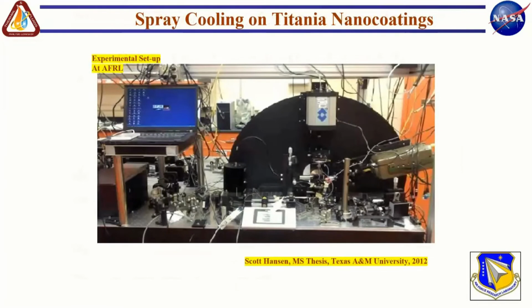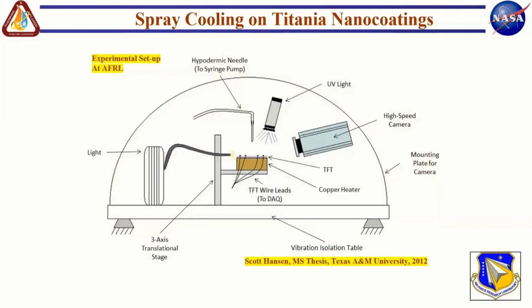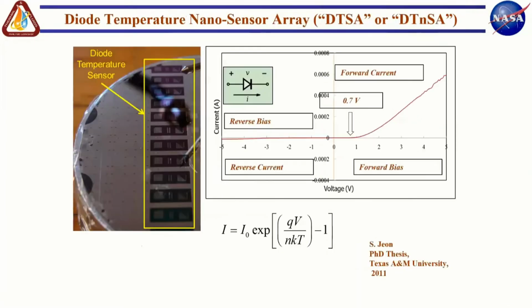One other work I wanted to showcase is Scott Hansen, currently at NASA Johnson. This was his master's thesis when he worked at Air Force Research Lab as a summer trainee, when I was there as a summer faculty, where we looked at these nanocoatings for spray cooling. And what we found was that with nanocoatings, the spray cooling was actually enhanced by a factor of 5 to 7, depending on the operating regime. So in the interest of time, I'll skip those results.